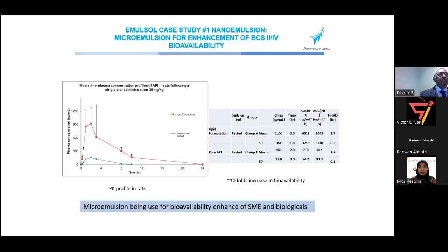The only thing is whether you look at the stability, how stable they are, right? You don't want the drug to crystallize as time goes on. So not only the thermodynamic, but also the kinetic stability plays an important role, right? So you take this molecule and throw it in water, and look at the kinetic profile, the release profile. You also don't want it to crash immediately, right? You want to make sure it maintains the supersaturation for a longer time, right? Like I said earlier, these are all important.